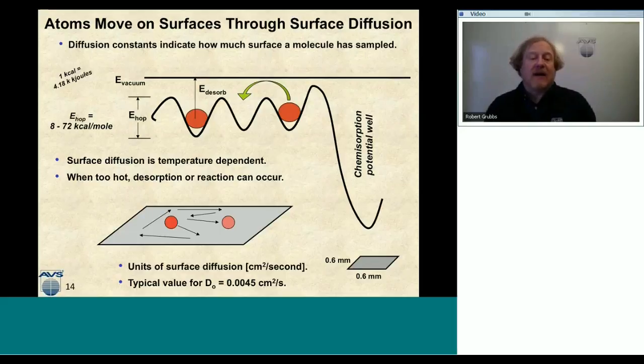Now, if we look at surface diffusion, the units of surface diffusion are given in terms of square centimeters per second. And so that is about the average area that a molecule will sample on a surface in 1 second. And obviously, if I increase the temperature, that value is going to go up, and I'm going to sample more surface area per second. So a typical value for a surface diffusion constant is 0.0045 centimeters squared per second.